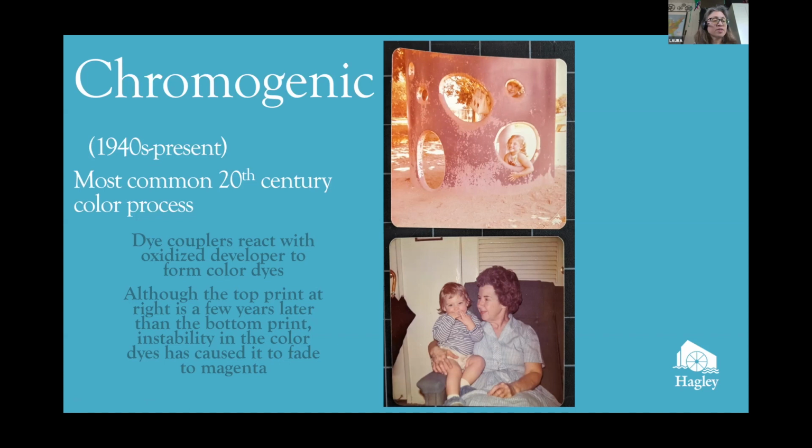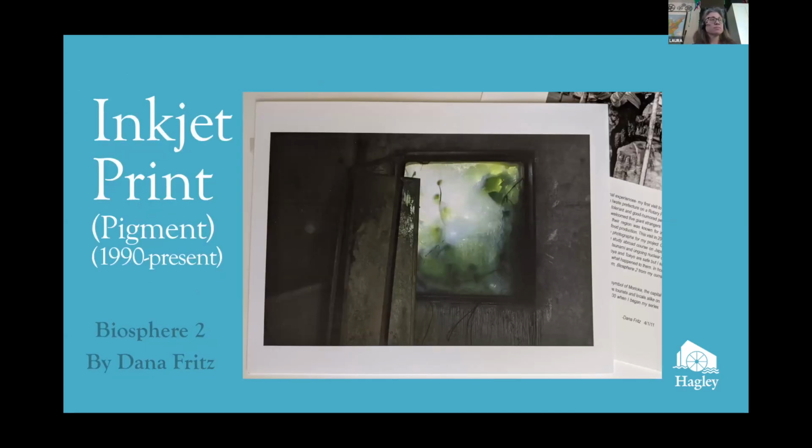Some chromogenic prints develop a yellow cast in the highlights caused by residual yellow coupler staining. Other prints may shift to a magenta tone as different dyes have different rates of fading. Unfortunately, these color changes are not reversible. Once the fading begins, it often continues even when the photograph is placed into cold storage or into the dark. Museums and archives store vulnerable color materials in cold or freezing temperatures to slow the chemical change and deterioration.